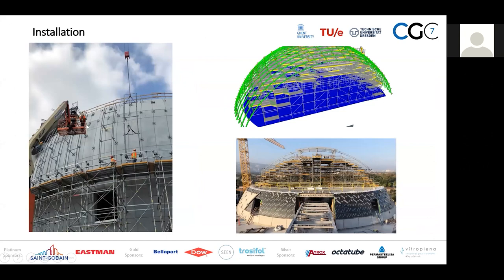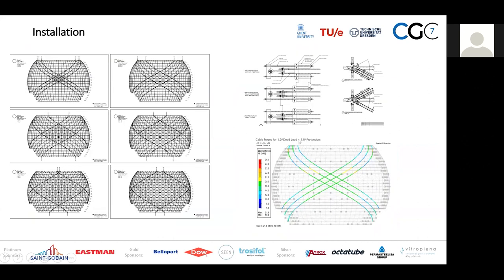On the next slide, you see how the installation began, starting at the base with these prefabricated ladders, and some intermediate members in the second step. Then there was a full scaffold on the roof terrace of the dome with the same ladder frames being supported on the scaffold, moving downwards, and the lower part moving upwards until it became a full structure. One of the most critical parts during construction was the pre-tensioning of the cables. It had to be done in an absolutely 100% symmetric way. You can imagine that when you start applying forces on the cables, you would immediately distort the entire lightweight shell structure. So there was a very clear plan, which was developed together with Gartner, from the engineering side by us, and from the installation perspective by them.